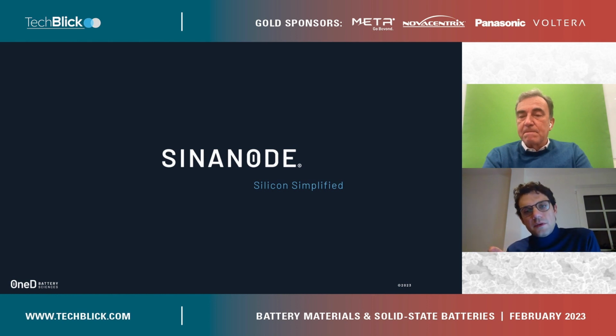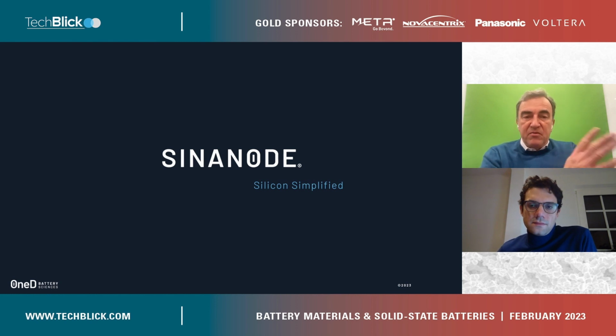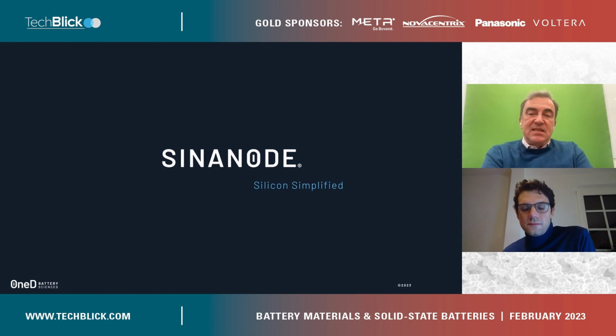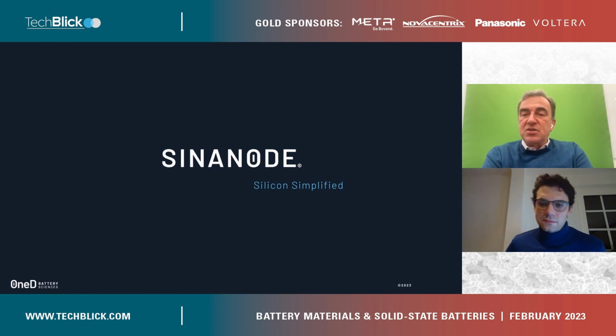Great. But what was the approximate number of cycles you achieved? So if you try to, for example, match silicon oxide, and you take a silicon oxide electrode from a commercial supplier that has 10% silicon oxide and graphite mixed together, and it's in full scale production, we can beat that both in terms of capacity and capacity retention over 1,500 cycles in EV cells. So you get a lower cost silicon, and you get better cycling and better capacity retention than 10% silicon oxide in EV cells.